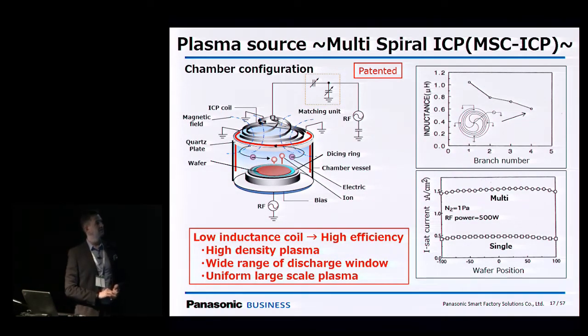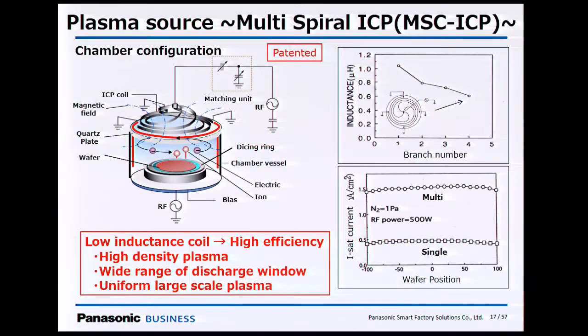Again, this is a detailed look inside the machine with a schematic. We have our multi-spiral coil ICP. The main point to take away from here is that it's a very high density plasma, and uniformity is one of our number one concerns. So if you have a 6-inch or a 12-inch wafer, whatever's happening in the center of the wafer is also happening on the edge of the wafer. So I always say, I don't think about yield on the wafer. It's either not 100% or 100%. During the initial phase, we have to develop the recipe. But once that's established, you should be looking at 100% yield, because the dicing will occur over the whole wafer uniformly.